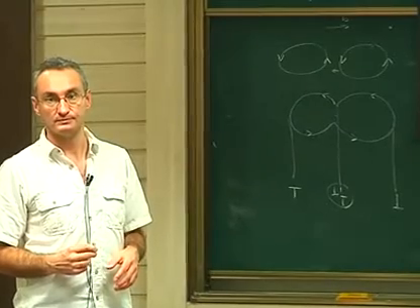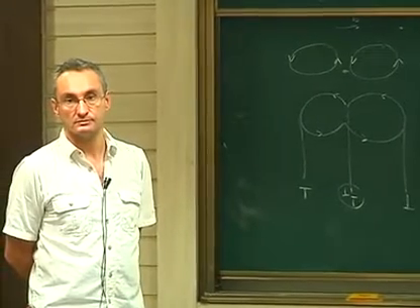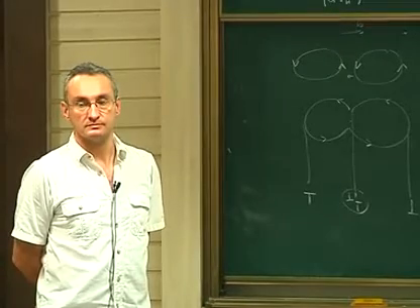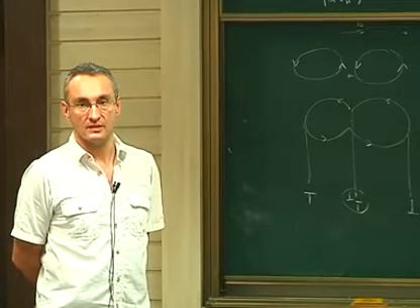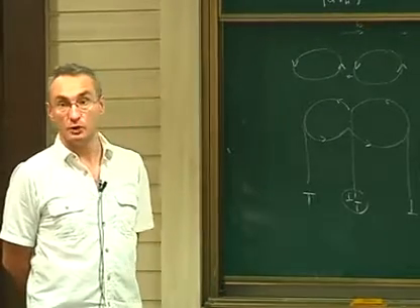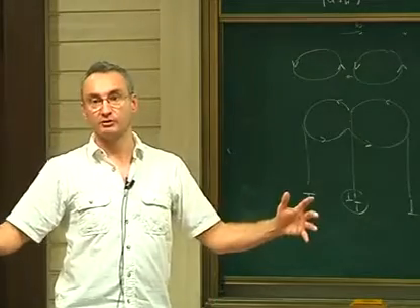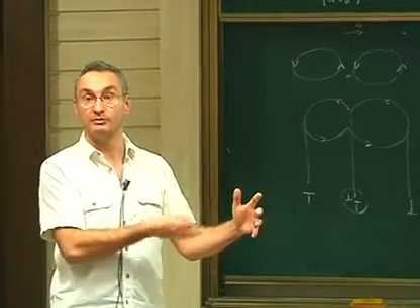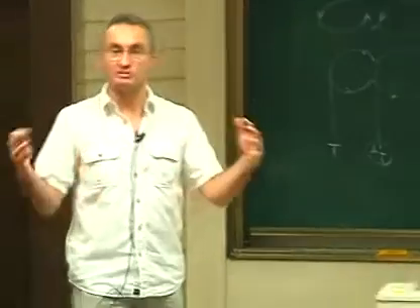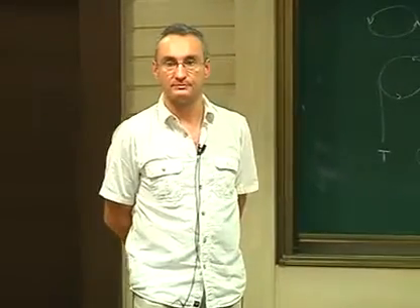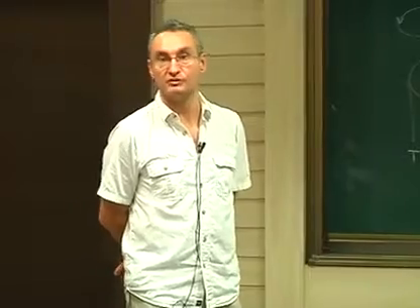Okay? So if the initial microstructure is there, and I populate it with Frank-Read sources which are lying on the same system, will hardening occur or not? If they're on the same system, I would say no. Unless you have some finite volume with boundaries where you have pileups. But that's not dislocation interaction, it's just pileup of dislocations against a boundary. Suppose it is PBC, then? PBC, periodic boundary condition, no, they will self-annihilate.